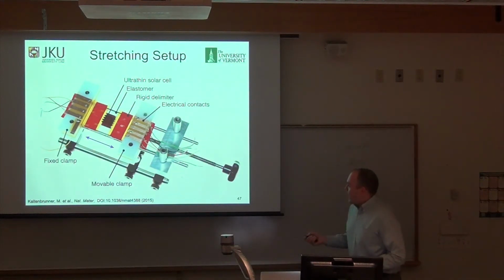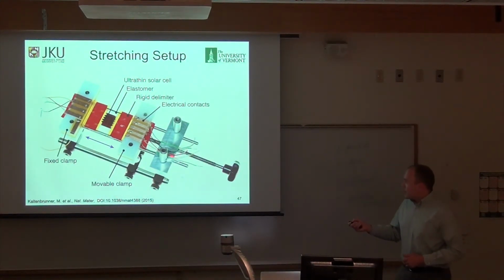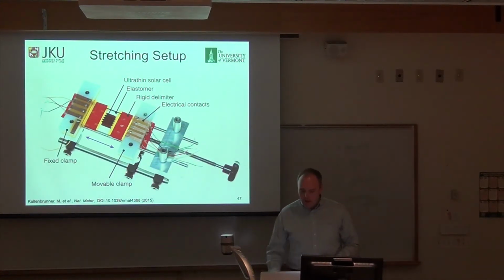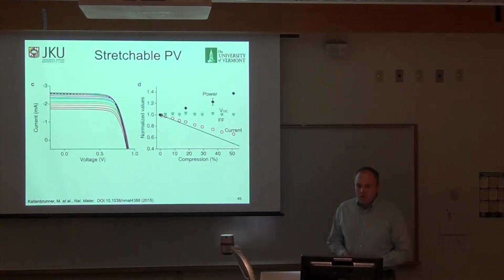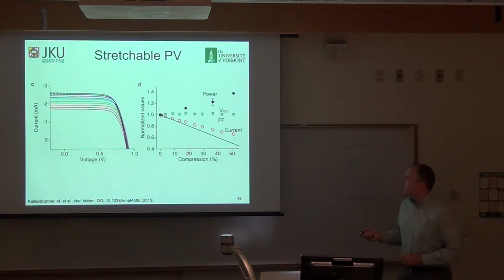We do that with a little jig where we can stretch the elastomer, put the device on, wire it up, and then relax and contract it, or expand and contract it repeatedly. And when you do it, the solar cells still work just fine. This is not too surprising to us by now.